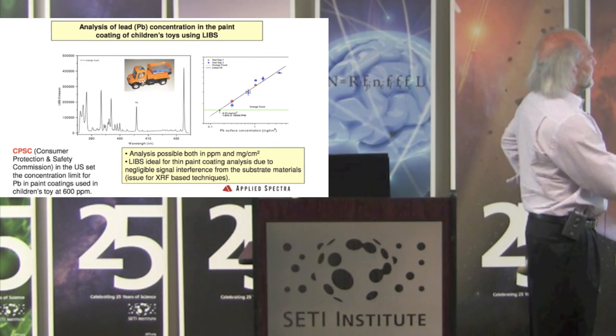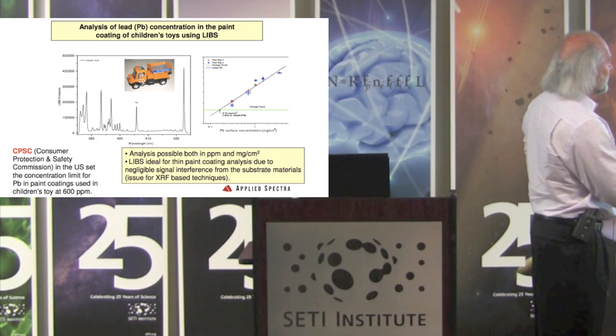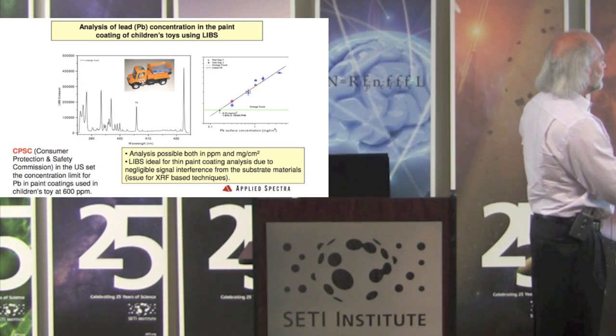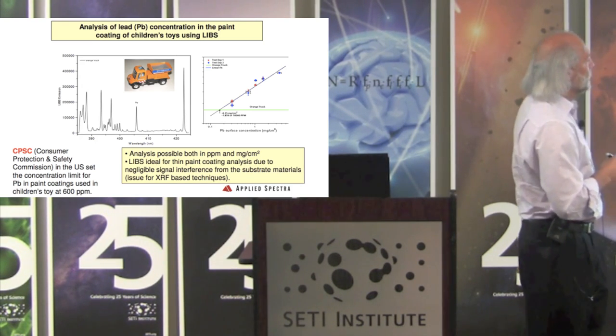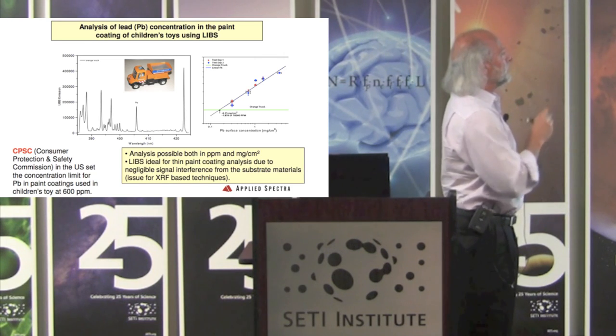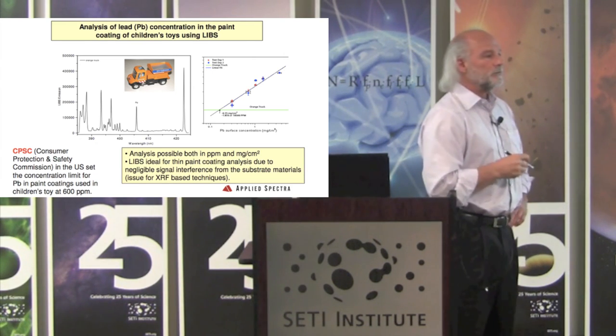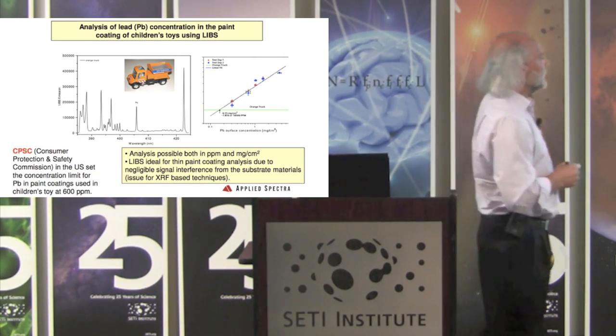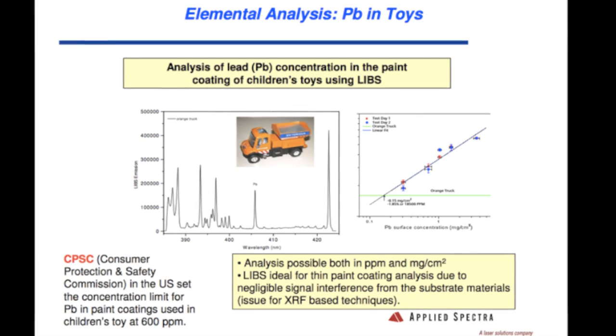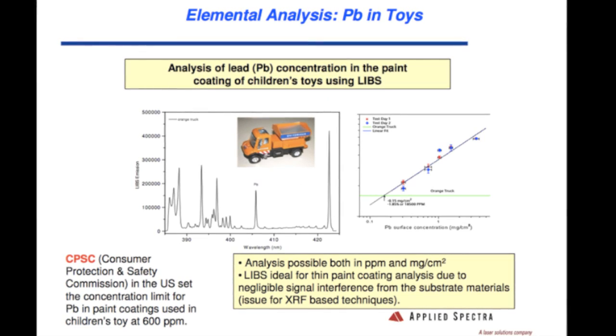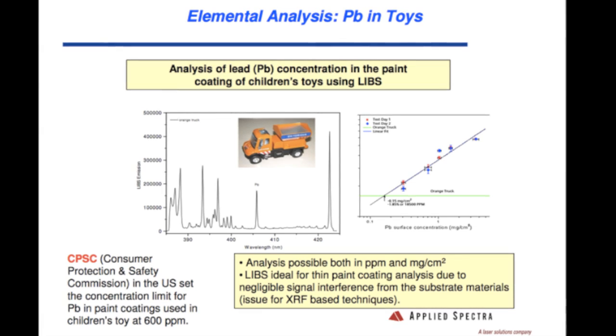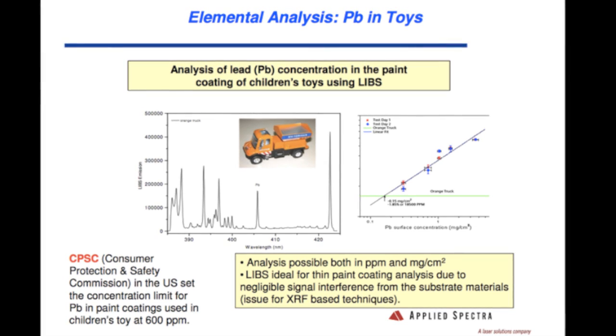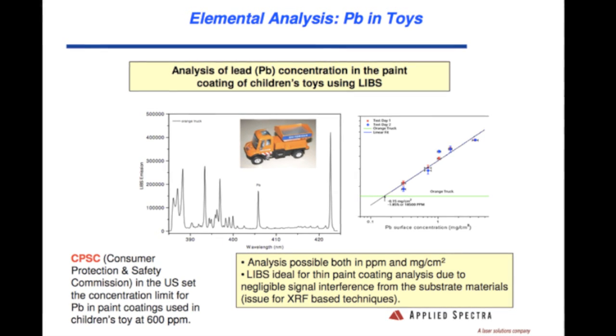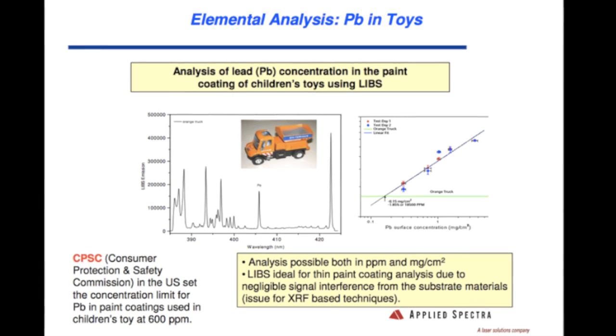You have a broadband spectra. In this case, it's not very broadband. It's in the UV, from 390 nanometers to 420. And we happen to be looking for lead in this little toy truck. This is something we did for the Consumer Protection Agency. So we take a little toy off the shelf at Toys R Us, which you can't do anymore because they've all been taken back. And we look for this one particular transition where we know lead emits a very strong signal. All right.